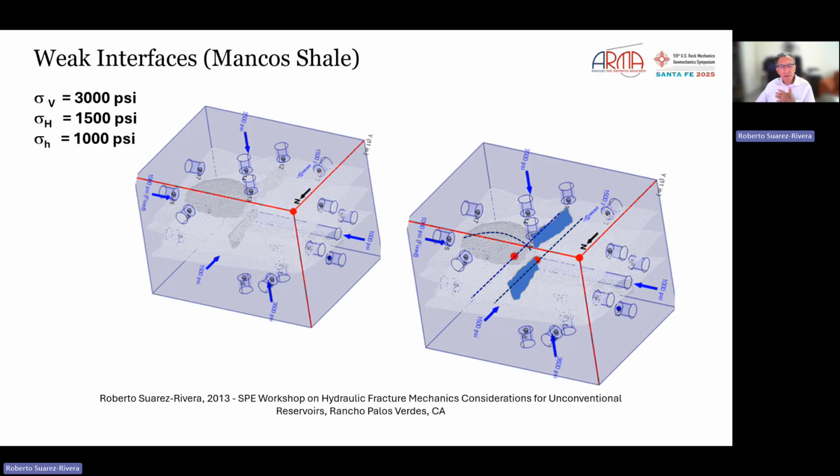Of course, after the fact, when the block was segmented and CT scanned and so on, we realized what was driving this issue. First of all, there was a concretion here, which is a more densified portion of the shale. And that dense system was making the distribution of the stresses non-uniform.